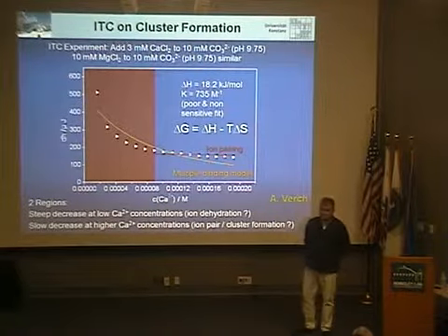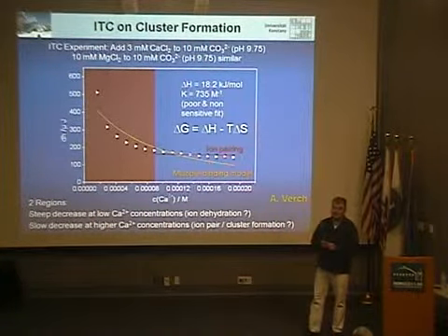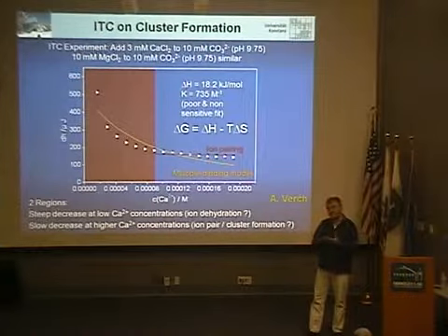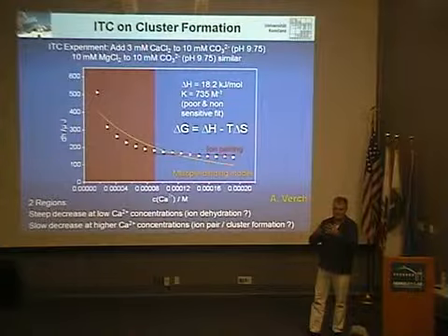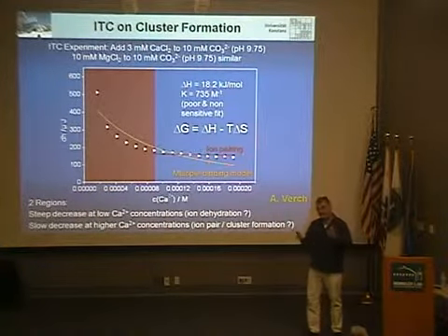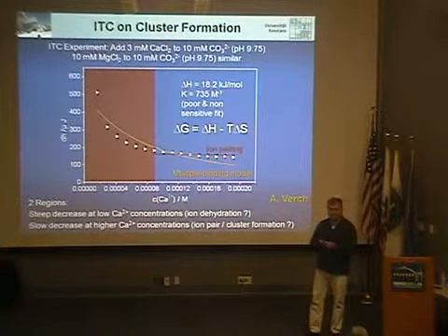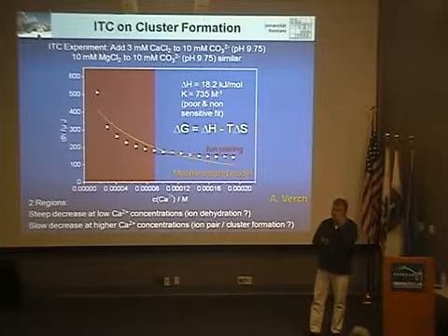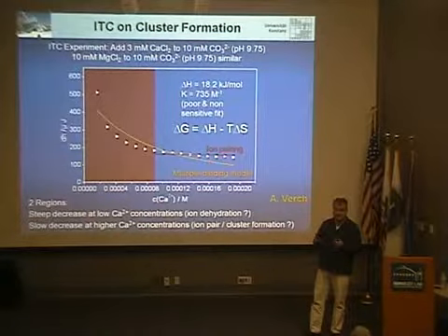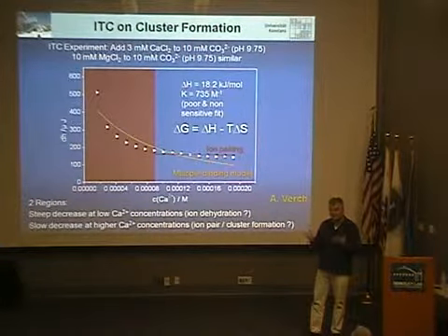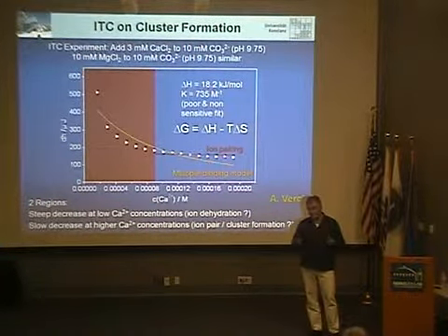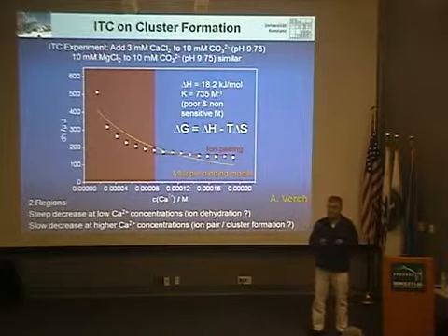We think they are dynamic. The reason is that whenever you try to separate them, they will precipitate, or if you dilute them, they will fall apart again. So it's a dynamic structure. We tried to do NMR experiments to capture the dynamics, but the concentration is so low that the NMR doesn't detect them. So at the moment, that's a problem. It's just speculation that they are dynamic. From the experimental evidence it seems to be, but we haven't proven it.